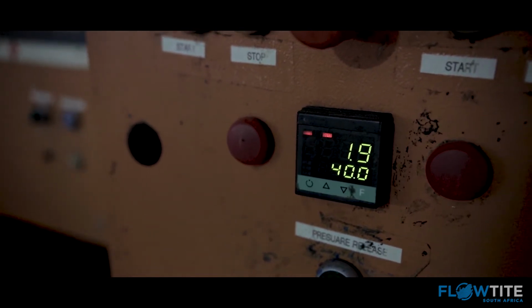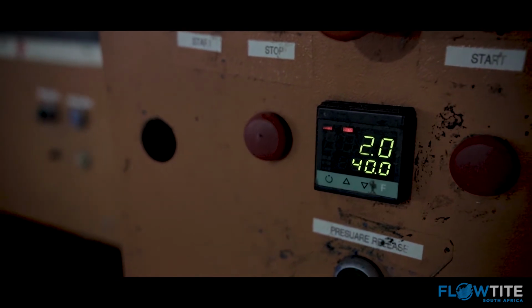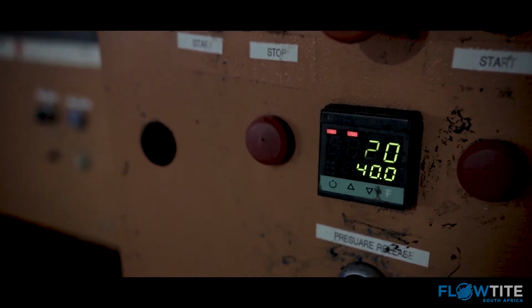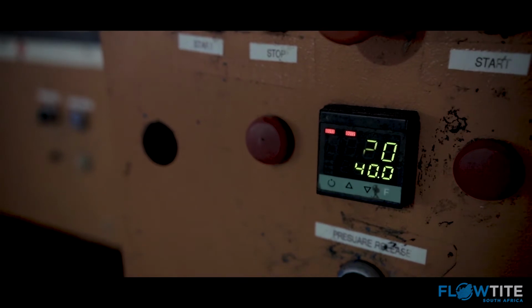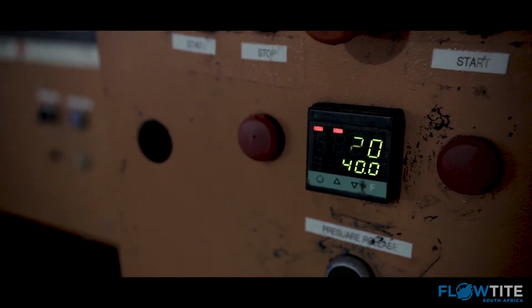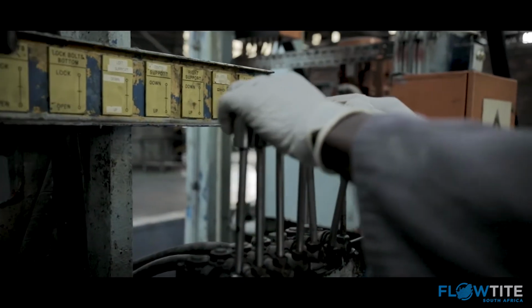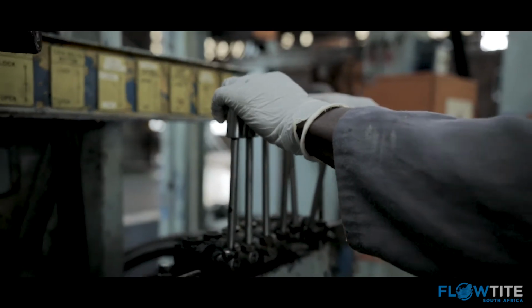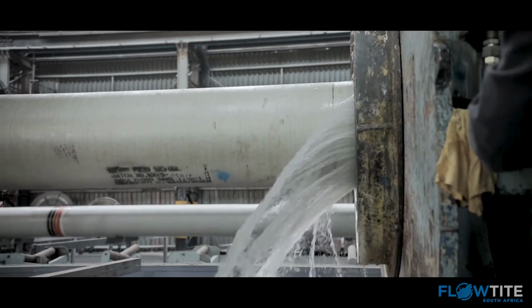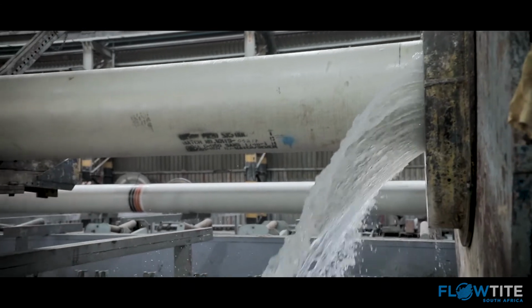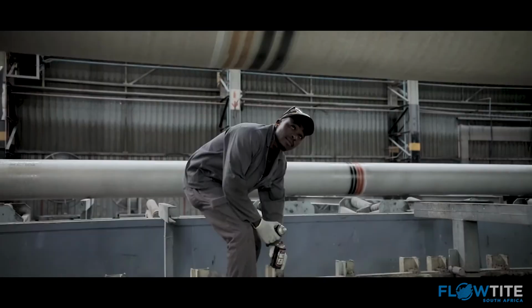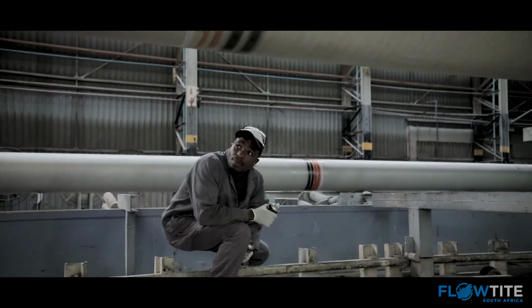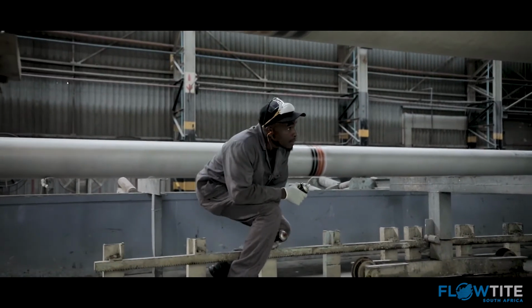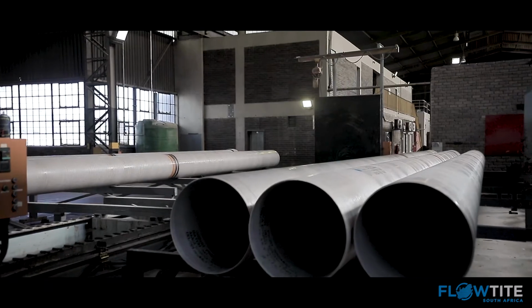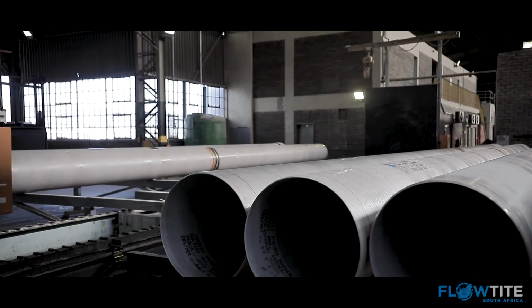Pressure is then applied and tested to double the pressure rating and kept under pressure for 2 minutes. After the pressure is released, it is then kept at a safe pressure where the pipe is then inspected for any signs of weeping or leaking. This is when pipe moves towards coupling insertion.